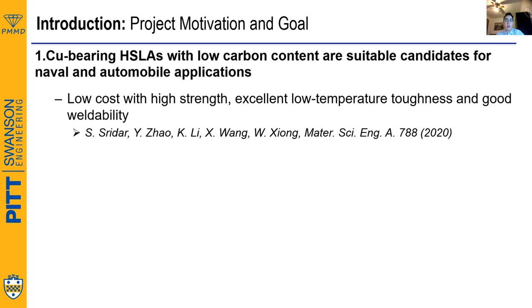First, the low cost and high strength. Second, the excellent low temperature toughness. And third, their good weldability. The low carbon content of these steels provides them with good resistance to hydrogen-induced cracking. The dissolution of cementite during the heat treatment provides the necessary carbon content for the precipitation of M2C carbides, which then imparts excellent impact toughness results.